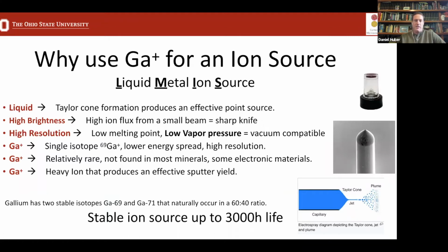That is a liquid interface phenomenon. And so what's really interesting about gallium is it has a very low vapor pressure and a very low melting point. So it melts just a little bit above room temperature, but has a very low vapor pressure, so it's vacuum compatible. Gallium exists in 2 isotopes, 69 and 71. In our sources, they're actually a single isotope source. It has a low energy spread, gives us a very high spatial resolution. It's a relatively rare element. It's not found in very many minerals and some semiconductor and electronic materials. It's also a very heavy ion that produces an effective sputter yield, which means when the ion from the source hits the sample, it's going to blast away a lot of material fairly effectively.